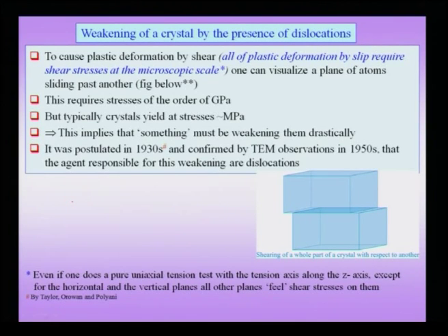Now suppose I want to understand plastic deformation or permanent deformation. I have two parts of a crystal, for instance, this is part 1 and this is part 2. I can shear one part with respect to the other by applying a shear force. But if you look at the stresses required to cause this kind of plastic deformation, it turns out to be of the order of GPa, which you will cite again in the next slide.